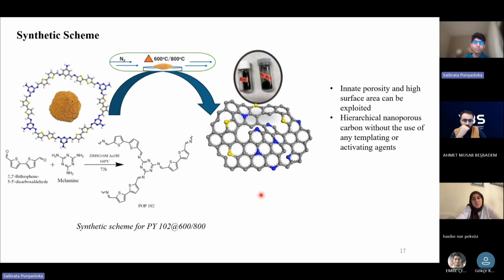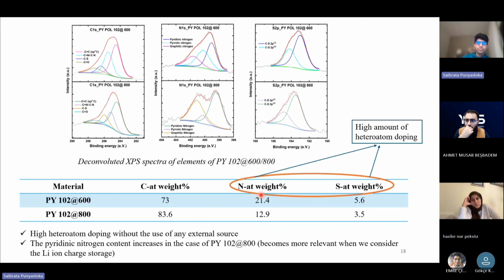Why I'm talking about high surface area is because more charge can get stored on the surface, and the higher the surface area, the higher the charge storage. So we can have higher capacity. But the downside is, of course, that such high surface area is also getting exposed to the electrolyte. So the electrolyte reduction will also be high. We can optimize that, but that is another separate topic altogether. Here I was just studying material properties. So yeah, this was the thing.